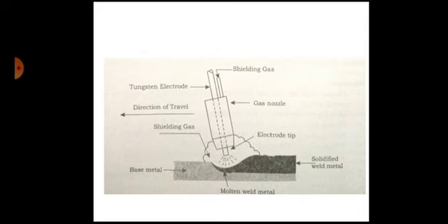Electrodes of tungsten are coated with thorium or zirconium to increase the current carrying capacity. Uncoated electrodes are suitable for currents up to 150 ampere, while coated electrodes can be used for currents of 220 to 250 amperes. Shielding gases like argon, helium and their mixtures, argon-oxygen mixture and argon-hydrogen mixture are used.